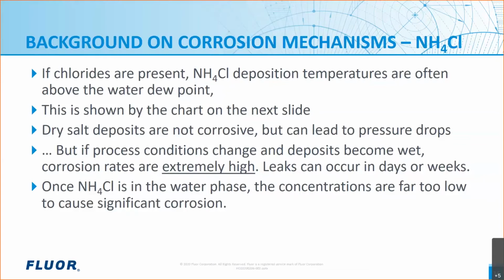But if the deposits are wet, and by wet, it doesn't even mean that you have to be below the water dew point, because the deposits themselves are hygroscopic and can absorb moisture just within the deposit. So there's not a bulk water phase, but the deposit itself can be what we're calling wet. If you get wet ammonium chloride deposits, the corrosion rates are extremely high.